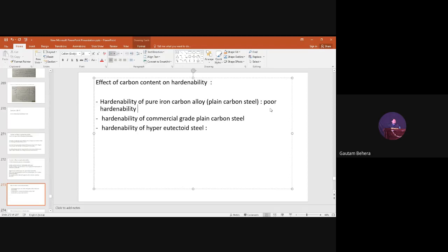This is relative. I am comparing, not saying directly. I am comparing the plain carbon steel with alloy steel. That's why it has poor hardenability. Even if you are doing quenching, you cannot get martensite everywhere, sometimes because of poor hardenability. Why? Because alloying elements are absent. And if alloying elements are absent, the nose of the TTT curve or CCT curve is not shifting towards the right. So we cannot have high hardenability, right? So this is the answer.